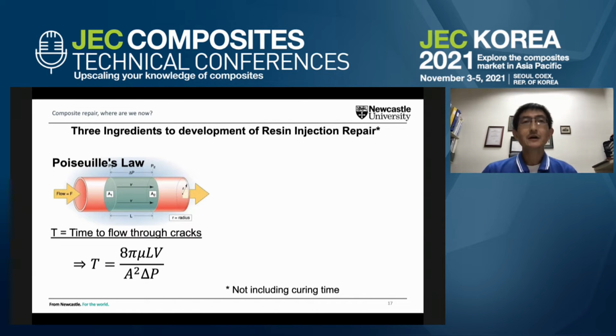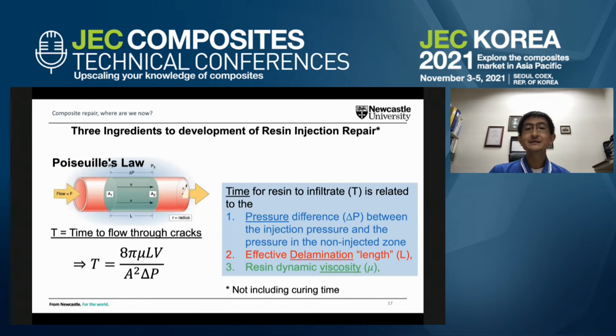And to deal with these three areas, there are also three so-called ingredients involved. And these three ingredients, which I'll be taking you through in the next couple of slides as to how we actually use them as parameters for understanding resin injection repair and developing a resin injection device that is useful, is first and foremost the pressure difference between the injection pressure and the non-injected zone in the crack, for instance, and then the effective delamination length for which the resin flows through the crack, and finally the resin viscosity.